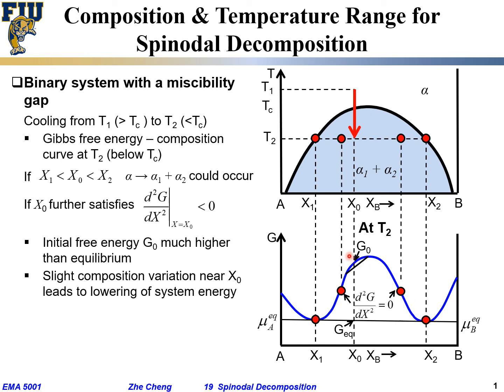In the beginning stage of spinodal decomposition, you cannot really tell exactly how it's happening even though it's going from one phase to two. There will be no distinct interface. The initial system is here, and after a little fluctuation it is slightly lower in free energy — it is always a spontaneous decomposition. Because there's no interface involved, there is no barrier to overcome. It's always downhill in free energy — a spontaneous process.